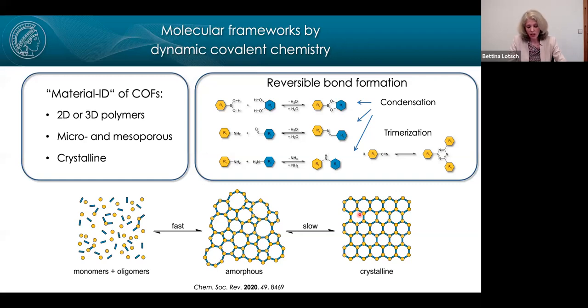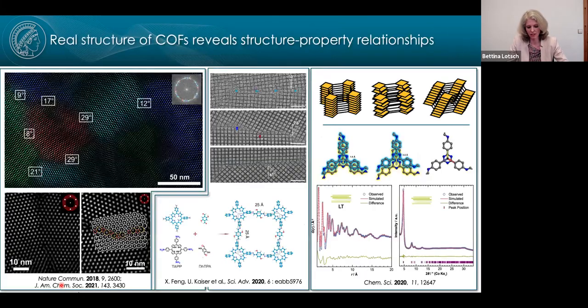Okay, so just because there is a mechanism of error correction, of course, does not mean that these systems are fully ordered or single crystalline. In fact, they are not, because the reversibility of bond formation is not perfect. And I just want to briefly make this point that there's very little known about the real structure of covalent organic frameworks, especially the type of defects and disorder in these systems. And in order to understand this, we need to do imaging, and we need to essentially make sure that we can use, for example, TEM or other imaging techniques on these systems. So recently, we and others have developed post-synthetic modification techniques in order to stabilize these frameworks.